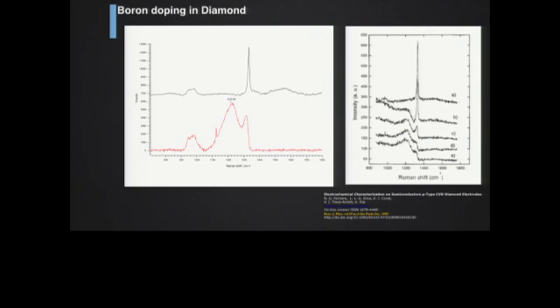We also have done Raman on the boron doped material, and as you begin to add boron to the sample, this is your baseline high purity diamond. As you add more and more boron, the Raman signal gets distorted like this here. So this is our sample here. This is some stuff that we found in the literature, and it sort of verifies another way of verifying that you have boron in the diamond.